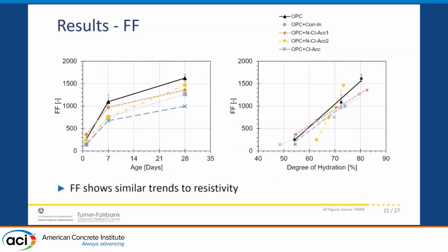And here instead is the formation factor. In the formation factor, we account for the pore solution resistivity, and it's got very similar trends compared to the bulk resistivity, so the control is always higher in terms of evolution over time. But again, once we account for the degree of hydration, not so much different except for one single admixture.